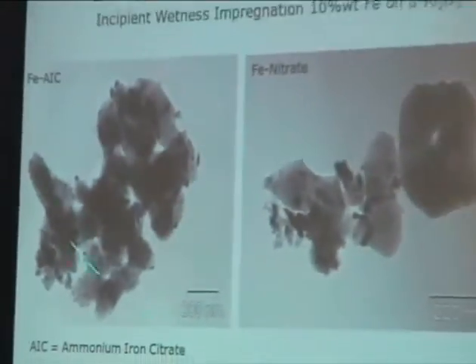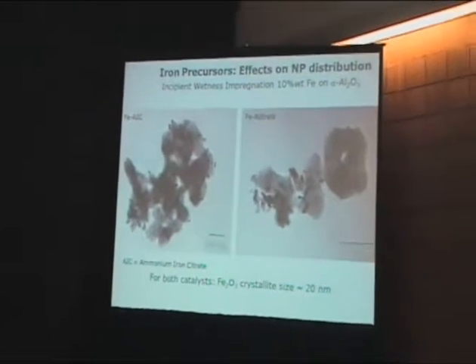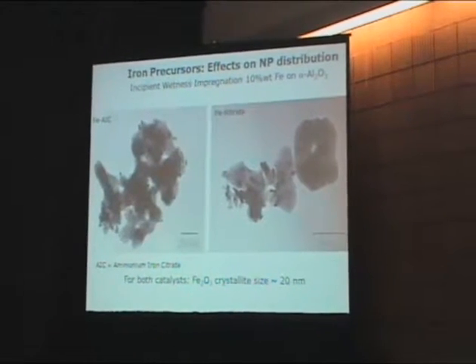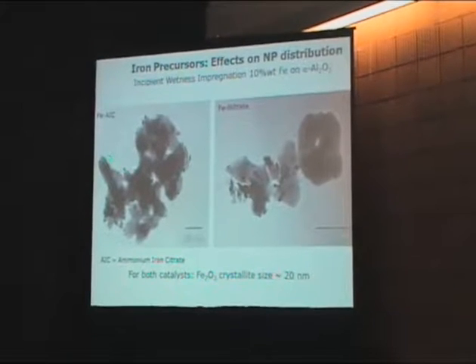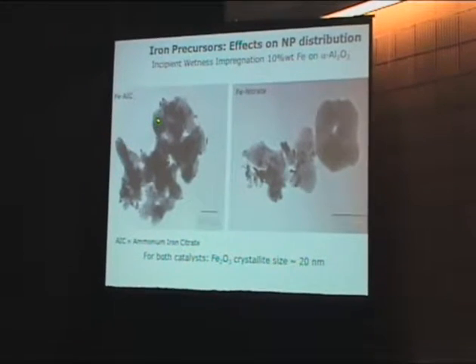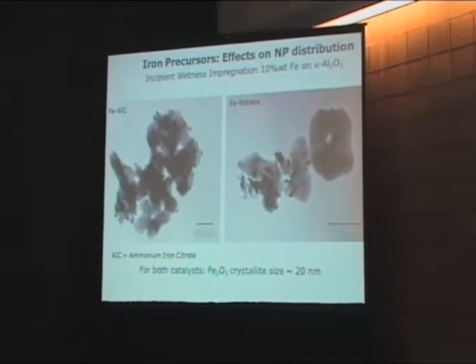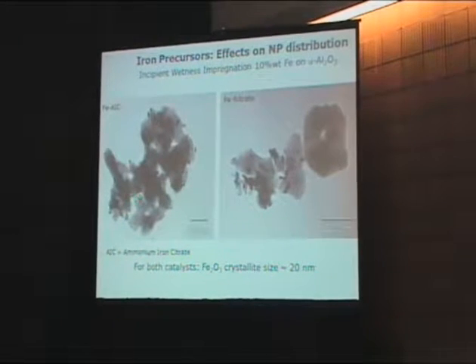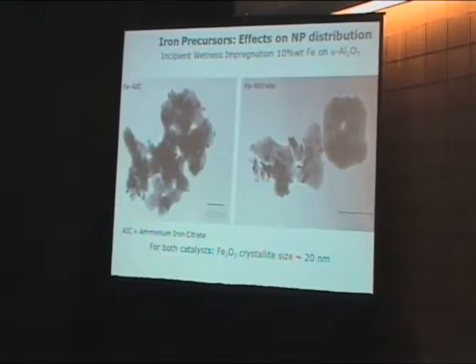If we use ammonium iron citrate as a precursor, which has a completely different impregnation, drying, etc. behavior, we see that we get very nice distributions of our iron nanoparticles over the support, much more uniform than in the case of the iron nitrate.